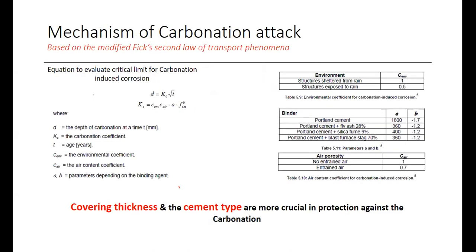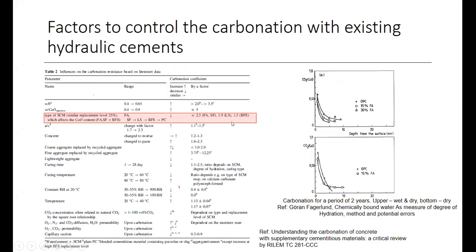So for that one, the mechanism is a bit different from the previous. It's also derived with the modified Fick's second law, with the transport phenomena. Here you can see the main parameters are the cover thickness, as we discussed previously, because the distance that carbon dioxide has to travel with time is a crucial factor. And the type of cement, which type of cement we are utilizing. So those are the governing factors to reduce the carbonation.